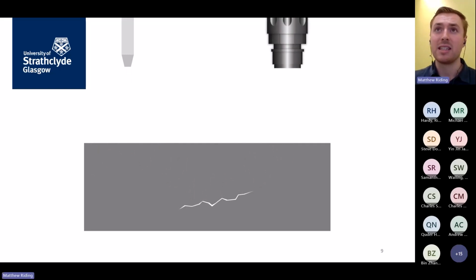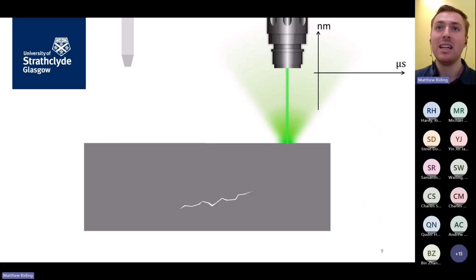We can then use a second laser system to detect the arrival of those echoes back up to the surface of the sample. This will output a plot of surface displacement over time, also known as an ultrasonic A-scan, and collects data that looks very similar to the piezoelectric transducers. So by this means, we have now an all-optical, non-contact ultrasonic transduction technique.